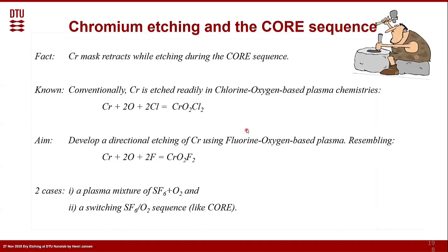So that's why we could find out that in fact the chromium is etched by fluorochemistry when you combine it with the oxygen. And that is because for chromium etching with chlorine, we know that the product is chromyl chloride, well known, and these chemistries are used to etch chromium, where they mix oxygen with chlorine, let's say 50-50%. But you can do the same with fluorine. And fluorine will not directly etch chromium, but it will attack chromium oxide.